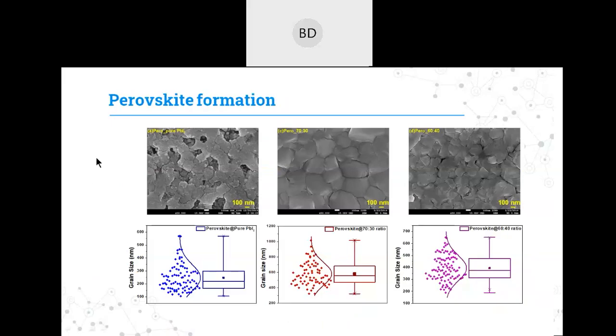We have prepared the perovskite from these precursor composition lead iodide morphologies, and we came to understand that the 70-30 ratio films give a very good morphology as compared to the pure PbI2 film. If you see the grain size distribution here, the perovskite in the pure case has a grain size of around 200 to 250 nanometers, but here the grain size has increased to 600-700 nanometers. Even some grains range up to 1 micrometer.